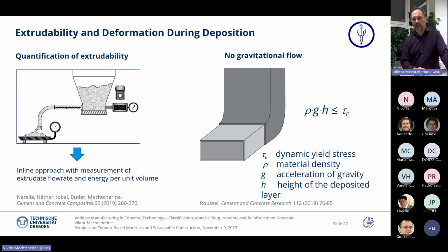And on the other hand, you are interested in the geometry of the filament after deposition. Basically, as long as the yield stress of the material, a dynamic yield stress in this case, after the deposition is higher than the density multiplied by the acceleration of gravity and the height of the deposited layer, then you will have no deformation, and in any other case you will have deformation of the material.